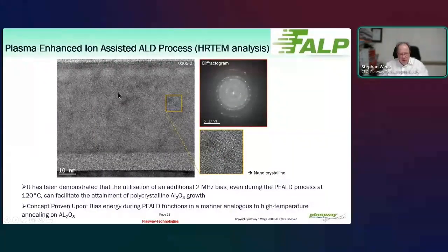And a new feature, what we found is what might be also interesting, and we will work on it in the next years: we have this aluminum oxide, like we saw before, but it is possible, when you bring in during the deposition some very well-defined ion energy, to create, instead of an amorphous film, a polycrystalline film. So here we will work together with the Leibniz Institute here in Dresden to make this really more reproducible and understand how we can control the polycrystallinity.